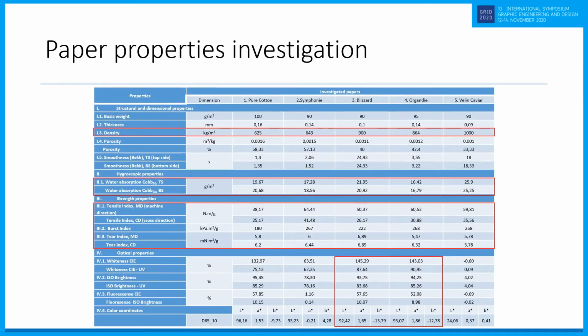The paper properties investigation was the second part of our work, and the results are presented in this table. The investigated papers have a basic weight in the range of 90 to 100 grams per square meter and thickness between 0.09 and 0.16 millimeters, but most interesting are the results for the density and porosity of the papers, because they have bigger deviations, which means that even at similar basic weight, papers will probably have different ability of embossing and engraving during the converting processes.